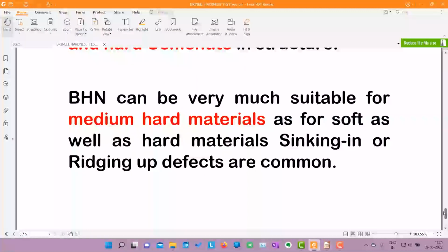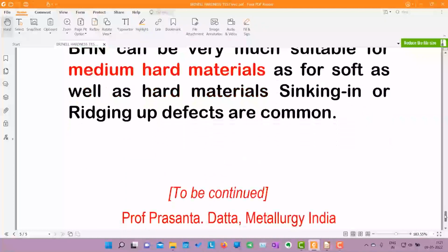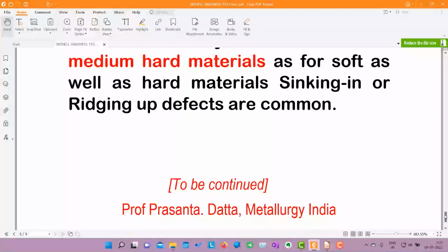BHN is very suitable for medium hard materials. For soft as well as hard materials, sinking in or ridging up defects are common. So for medium hard materials, BHN is generally used. It should not be used for very soft materials like lead, zinc, etc., or in hardened steel, because the ball is already a hardened indenter. So in those cases, there is a chance of defect. This is so far about the Brinell hardness test, and we will continue this program in the next lecture with the Vickers hardness test.